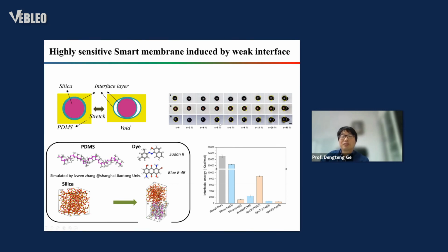We also found that when we coat the surface, the micro beads more easily generate a crack at a lower strain. So here we use silica nanoparticles in two steps. One is to spray on the surface, and then spray the dye solution, cure the surface, cast, and peel the membrane. From the video, we can find the top one is a normal silica PDMS membrane. The bottom one is silica PDMS with dye. So if we introduce the dye, it easily causes opacity.